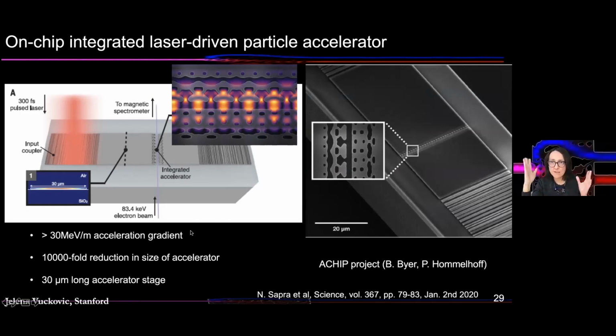And keep in mind that this is just a single stage of the accelerator. Even in traditional accelerators, you would have a lot of stages, and each one would accelerate particles more and more until you reach the target energies. So what we did here so far is just a single stage, but in the actual system, there would be hundreds or thousands of these stacked together on the same silicon chip, which is certainly possible because each stage takes only 30 micrometers.